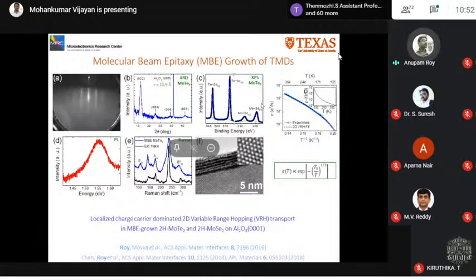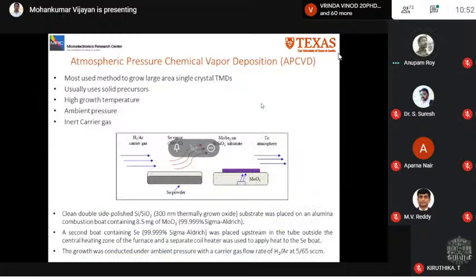I'll now discuss the other growth method, chemical vapor deposition, in the next slide. So the most widely used method for growing TMDs via chemical vapor deposition is the atmospheric pressure CVD. And as the name suggests, this entire process takes place under ambient pressure. And solid metal oxide, MoO3, and chalcogen powders, here selenium, are used as the precursors, and growth occurs at very high temperature, usually above 750 degrees C.